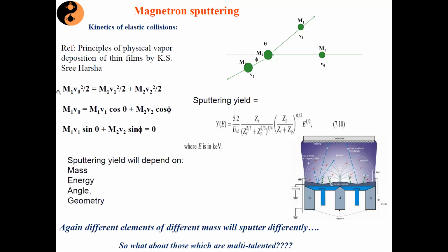This was the mass which is impinging on your target material, and this is the mass with which your target material is actually ejecting out. Okay, so just by solving this particular equation, what you will get is that the sputtering yield, that means the number of elements which are coming out from the target material, again depends on the atomic mass of the elements present in the compound.